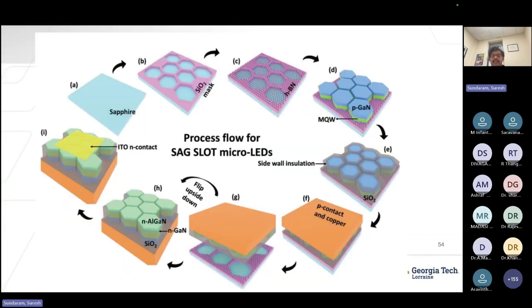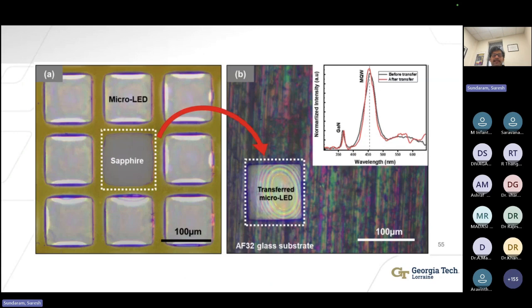So this is the overall process as I showed you before. Not only that, we can transfer only 1 pixel to any suitable substrate. Here you have an array of micro LED structures. You can transfer only 1 LED to glass or wood or anything, contact it, and get light out of it. Comparing before and after transfer, there is no change in optical and structural properties, because everything is retained. There are no cracks or mechanical defects due to this transfer process.